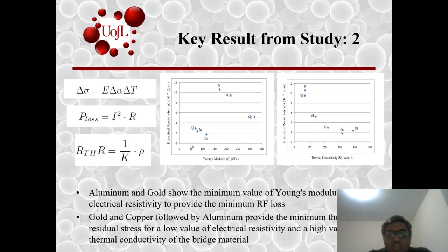So since they were interested in the less Young's modulus and the less electric resistivity, they concluded that aluminum and the gold showed the minimum value of the Young's modulus and the electric resistivity, and those materials are good for the minimum RF loss. And in the third plot, which is electric resistivity versus thermal conductivity, and since they were interested in the materials